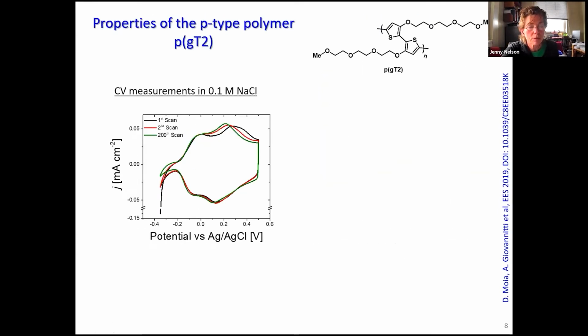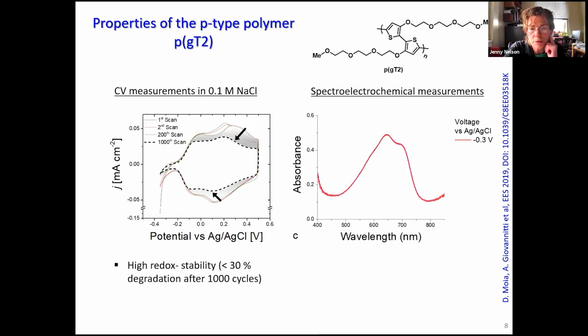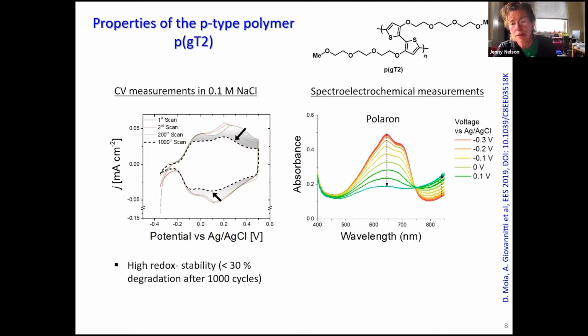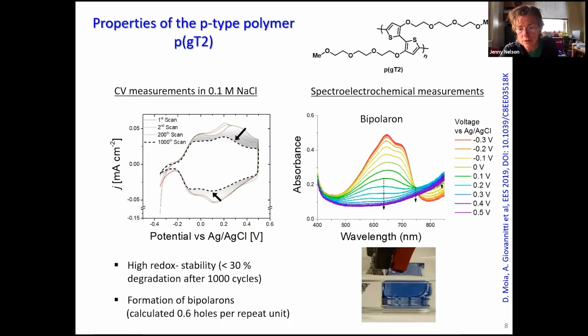Looking at the properties of the p-type, this is just showing the CV response, a reasonably reproducible CV response, with a bit of loss of performance after thousands of scans. What is very nice about these materials is that because they're conjugated polymers, their state of charge is very easy to detect with an optical probe, because as you charge the material, you form polarons and eventually bipolarons, and they appear as changes in the optical spectra, and of course changes in the color of the device. In the case of this p-type, as you cycle it, you see its color change from blue to transparent as this ground state absorption band is removed and replaced in the visible.